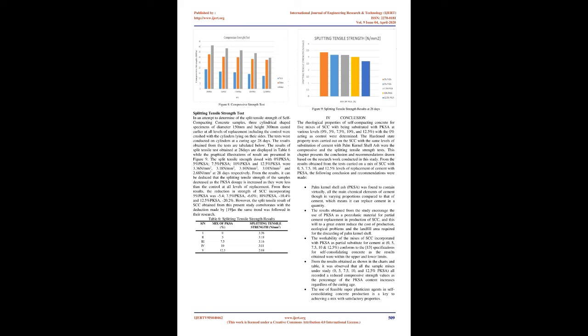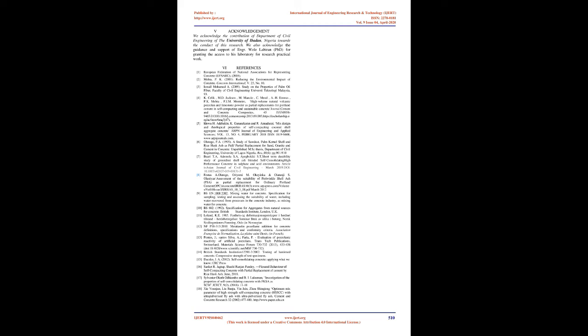The results of split tensile test obtained at 28 days are displayed in Table 6, while the graphical illustration of the result is presented in Figure 9. The split tensile strength of concrete dosed with 0% PKSA, 5% PKSA, 7.5% PKSA, 10% PKSA and 12.5% PKSA were 3.36 N/mm², 3.18 N/mm², 3.16 N/mm², 3.01 N/mm² and 2.68 N/mm² at 28 days respectively. From the results, it can be deduced that the splitting tensile strength of the samples decreased as the PKSA dosage is increased, as they were less than the control at all levels of replacement.